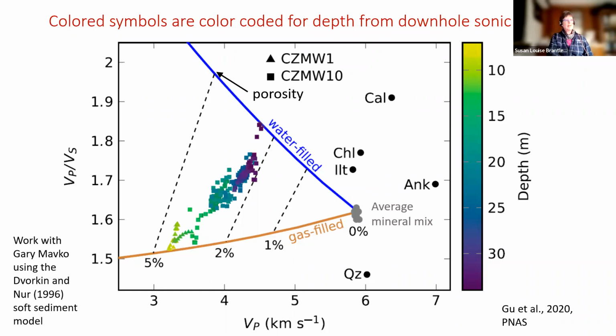And basically, with sonic logs down the borehole in the outlet of the watershed, we were able to measure P wave velocities and S wave velocities. And then in a plot of the P wave velocity versus the ratio of P to S wave velocity, here are the data for that borehole. And they're color coded by the depth.